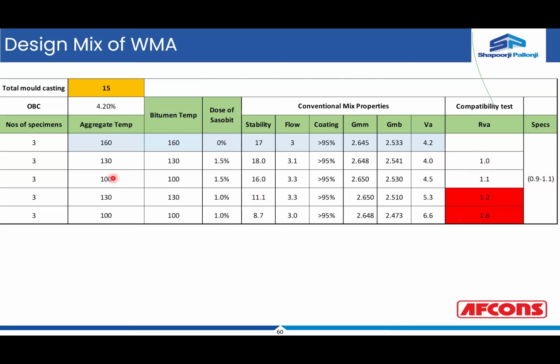Similarly, if you are reducing the aggregate temperature to 100 and your bitumen temperature to 100, and you are adding Sasobit at a similar dose of 1.5%, the stability goes down a little, the flow increases, the coating ability has no change, the GMM is slightly increased, GMB has slightly reduced, and the air voids are slightly increased. The increase in the air voids indicates that there is a possibility of reduced compaction during the construction phase, and then the ratio is 1.1, which is touching the maximum limit.